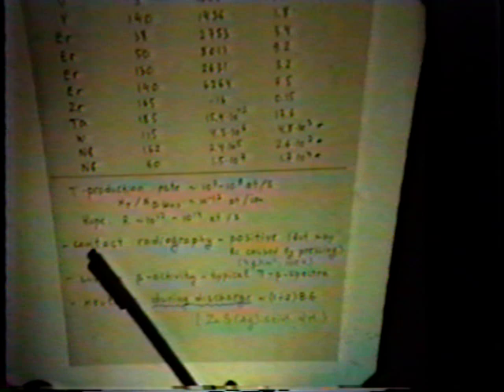This group also performed contact radiography and measurement of surface beta activity, both with positive results. They also measured neutron emission during discharge, and they observed only a slight excess above the background level. So their conclusion is that the tritium channel is much more efficient than the neutron channel.